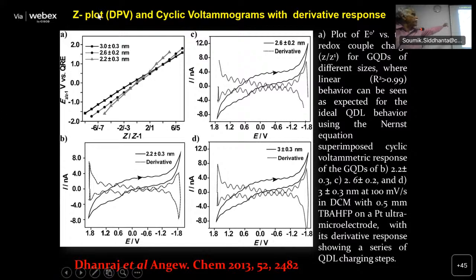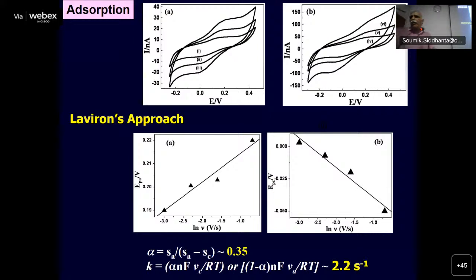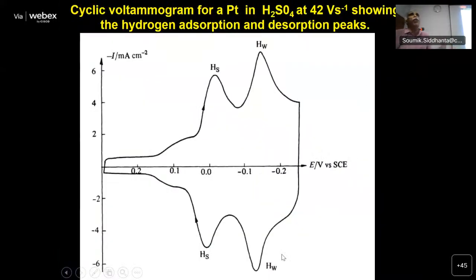And you look at this E versus Z. Z is the charge number. The diffusion coefficient of these particles can be obtained by using cyclic voltammetry. Again, I will not go to details. When such a phenomena happens, adsorption also can be understood much more thoroughly by using voltammetry. We use an approach called the Laviron approach. Laviron has done a lot of work on adsorption systems. As a function of scan rate, you plot voltammograms, plot peak potential versus scan rate, and you will get a logarithmic expression. Again, I will not go to details. I only want to tell you that whenever adsorption is rate determining, the Laviron approach enables you to calculate the rate constant of adsorption. For example, here 2.2 second inverse. So all these are possible by using cyclic voltammetry, provided we understand it quantitatively.